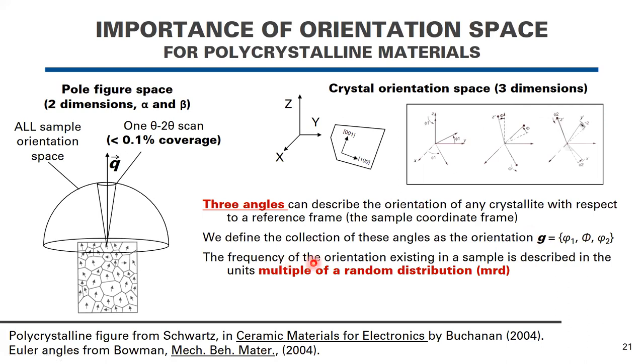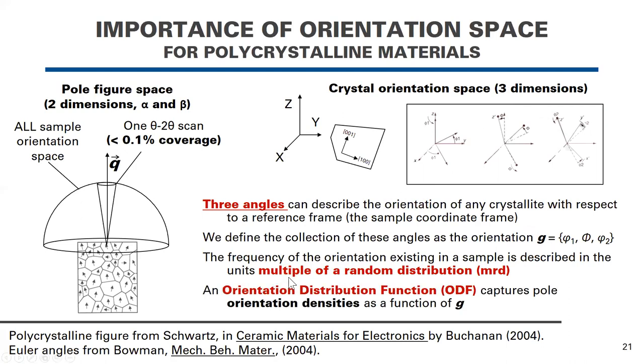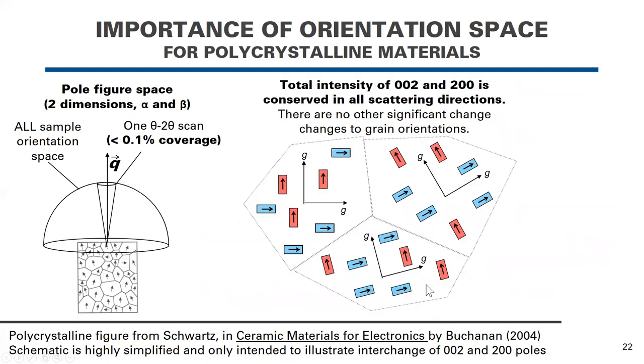And the frequency of any orientation existing in a sample is described in the units, again, of multiples of a random distribution. And so from this, you could create an orientation distribution function that captures the pole or orientation densities as a function of g. We're not going to do that today because it's an intensive process, but it's one that I think is very valuable. Now, an important takeaway from looking at pole figures and looking at domain switching is that the total intensity of the 002 and 200 is conserved in all scattering directions. And this provides significant value to us.